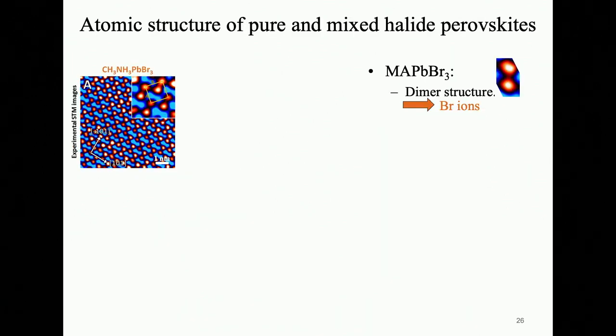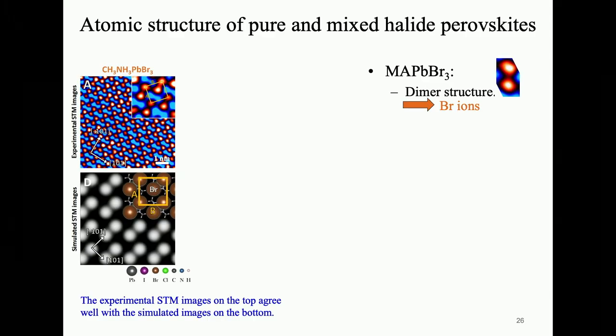In this study, the first sample we scanned is the pure MAPbBr3 perovskite sample. The top image is the experimental STM image, and the bottom is the simulated image according to the DFT calculations. As you can see, once again, we observed the characteristic repeating bromine dimer structure, and the top experimental image agrees quite well with the simulation image.